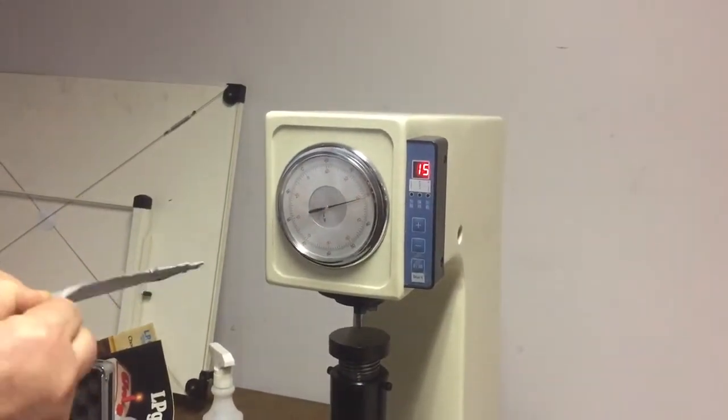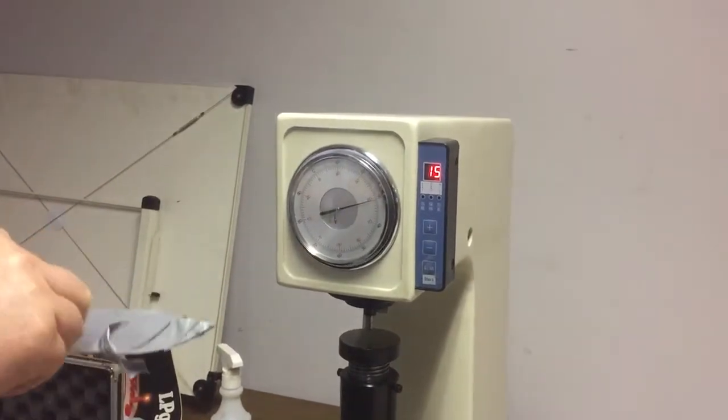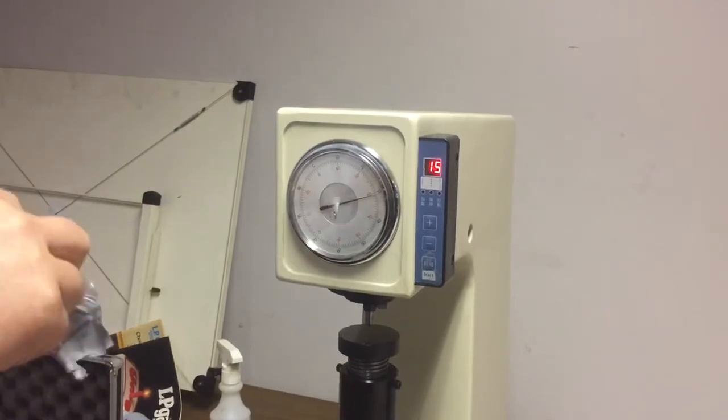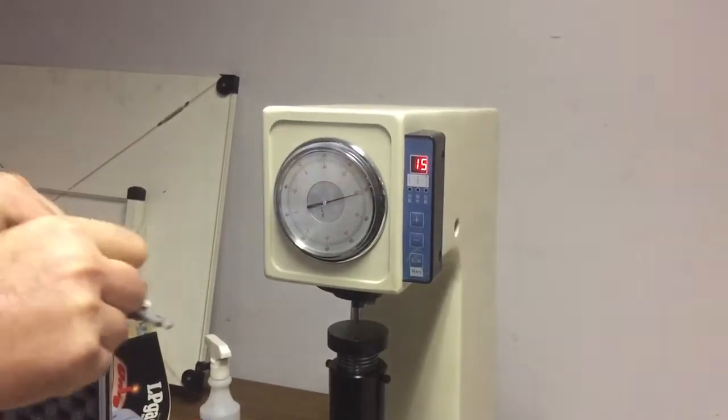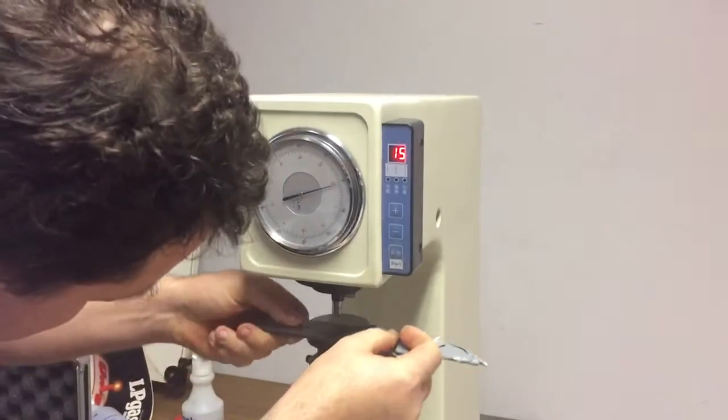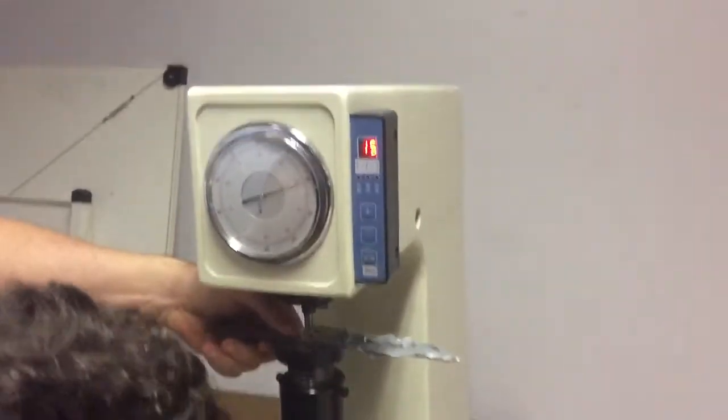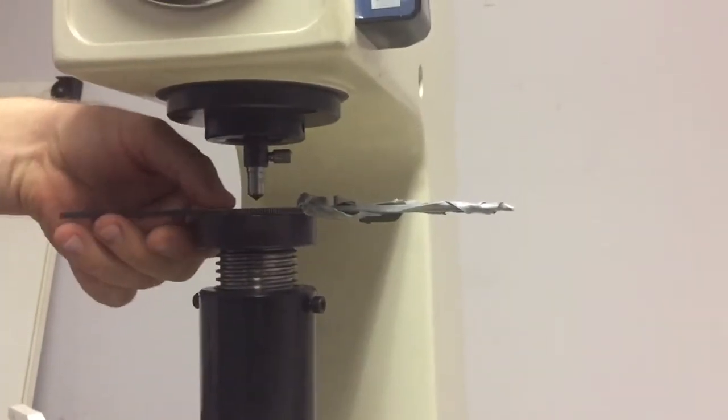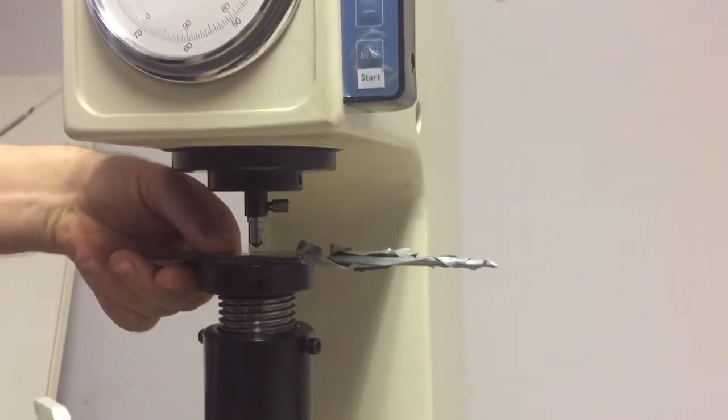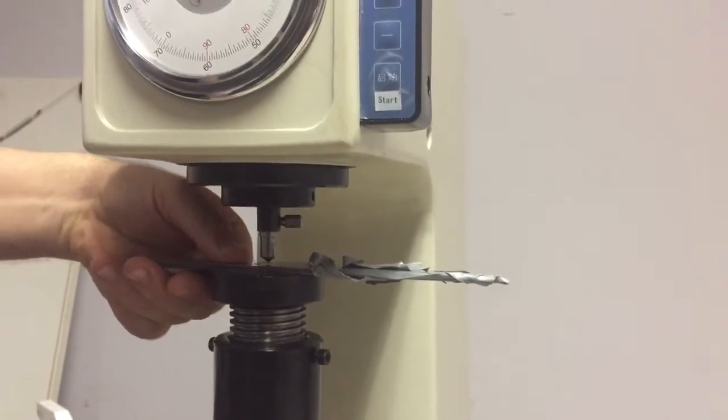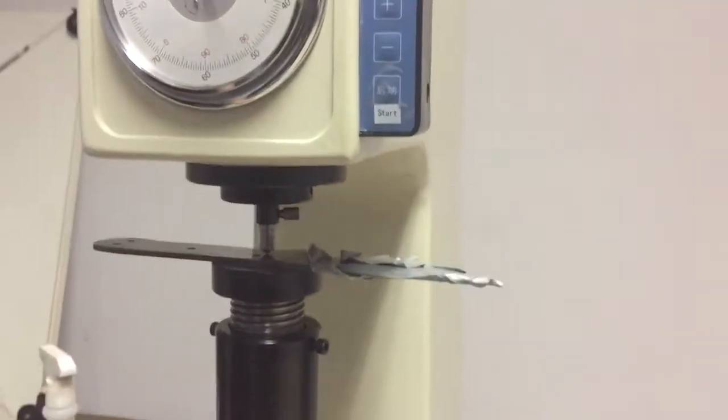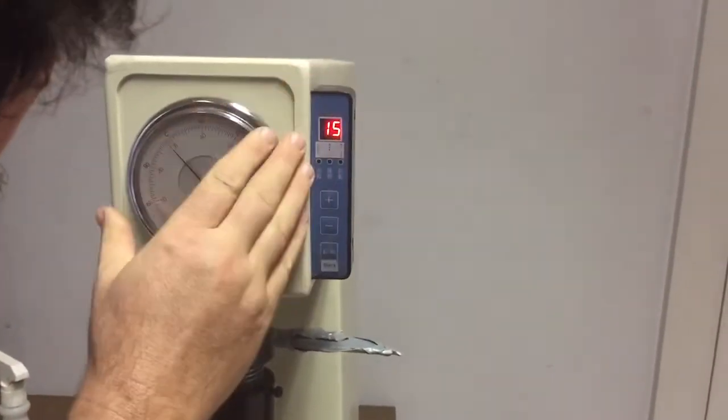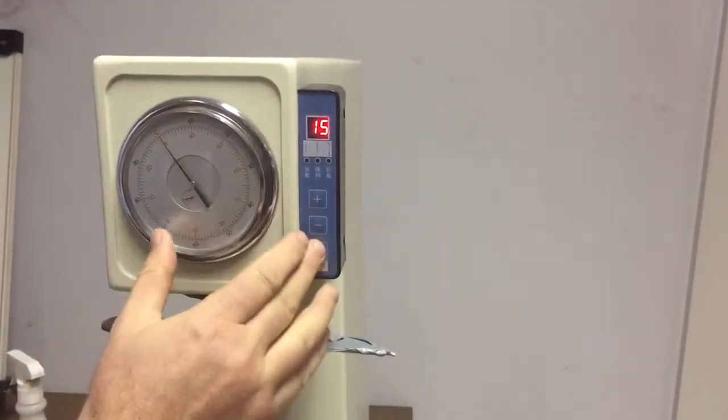Can't remember what steel or spec, but it doesn't really matter anyway. For the purpose of hardness testing, all that really matters is that we get a good result there. So it's very important that it sits flat. I often like to get my head down and make sure there's not a gap of light, which there isn't. He's got a very straight blade here. We're going to again preload the blade to the red dot. Just make sure it's on point there. Press start.